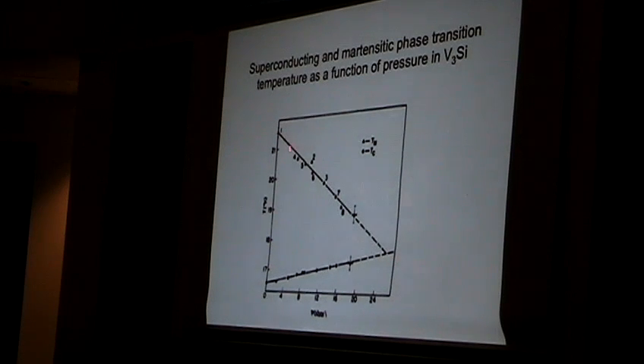And this line here is a so-called martensitic distortion. This represents a lattice distortion of this cubic lattice into a tetragonal state. Hans Otto has examined what happens beyond this point here, and it is not lattice distorted below this point. So ask yourself, there's essentially down here a coexistent state of a lattice distortion plus superconductivity that does not exist beyond this point. How can superconductivity quench this distortion?